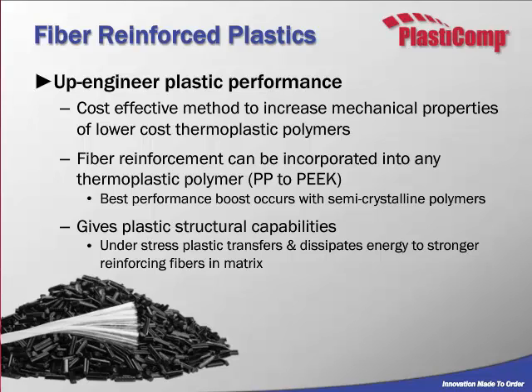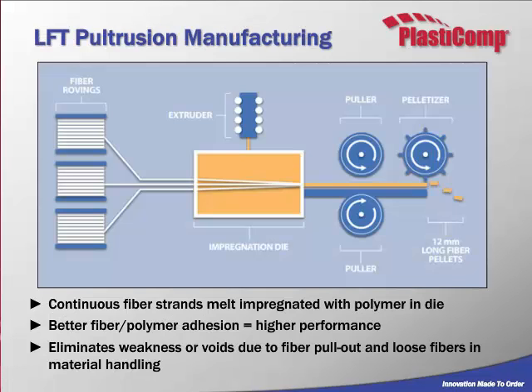Now we will focus solely on long fiber today, and we're going to cover some of the differences from short fiber materials. And one of the main differences is that the manufacturing process gives us the ability to maintain longer fiber from the start. So if we look at how long fiber materials are processed, we start with a continuous tow of fiber. We're dragging that fiber through a melt impregnation area, and that is our die, where materials are melted at high temperature and the long fiber material is pulled through and exits the other end of the die, where we have very specifically sized orifices.